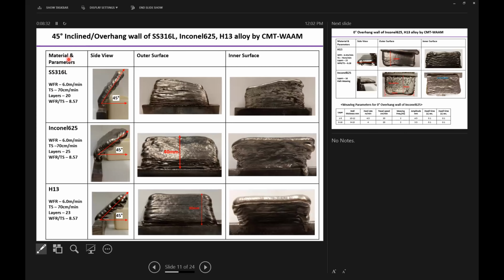And we also deposited the 45-degree incline wall for this material. Here we observe that for all these cases, the surface finish of the SS316L walls was poorer as compared to the Inconel and H13 alloy.